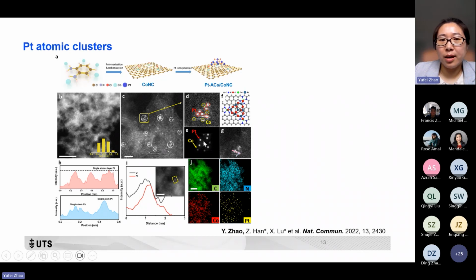So we also did a simulation. If we assign these bright dots to platinum and these lower bright dots to cobalt, it shows quite a similar morphology to the experimental result. That means it may form a close interaction between the platinum and the cobalt. The strong interaction may modify the electron structure of the platinum and the cobalt. And here is a line scan. If we do the line scan on the similar bright dots, we can see it can form a single atomic layer of platinum. If we do the line scan on the different contrast dots, we can see the close interaction of the cobalt and the platinum.